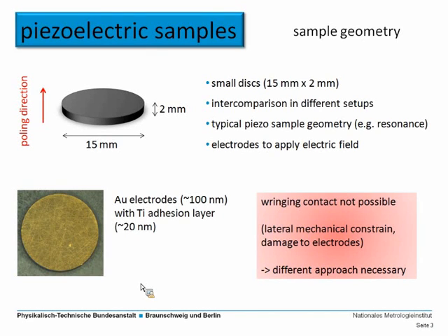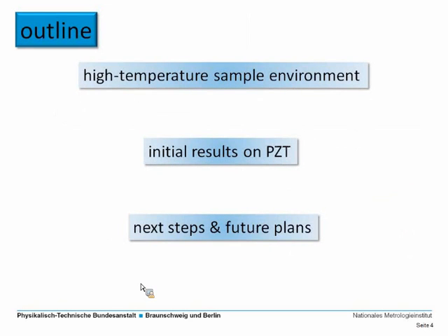And imagine if you apply a field to the piezoelectric sample, then the sample expands in the poling direction, and it also has to contract laterally, and this kind of contraction would be inhibited or disturbed by the wringing contact. So we had to find a different approach for the sample mounting.